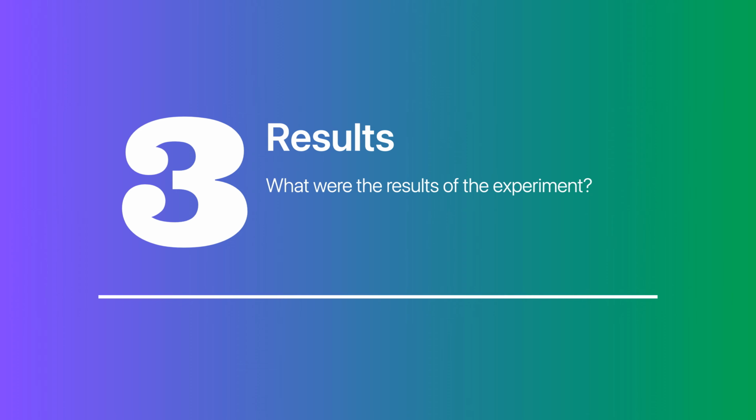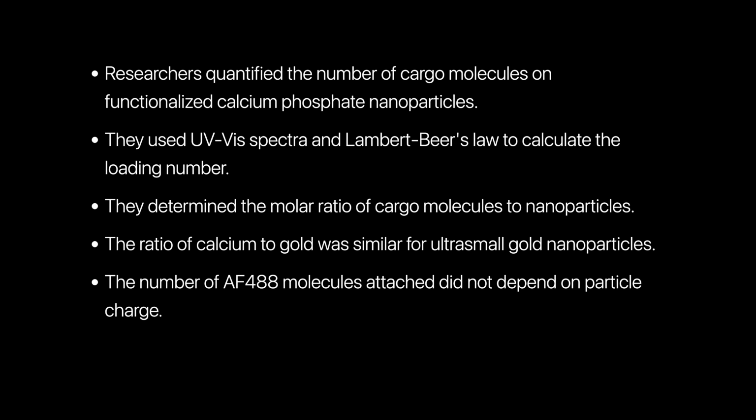3. What were the results? The researchers quantified the number of cargo molecules attached to the functionalized calcium phosphate nanoparticles using UV-Vis spectra, Lambert-Beer's law, as well as calibration curves. They were able to determine the loading number by calculating the molar ratio of cargo molecules to nanoparticles.